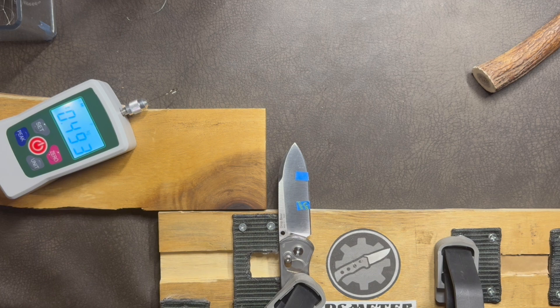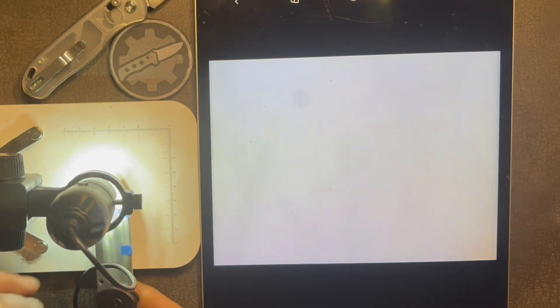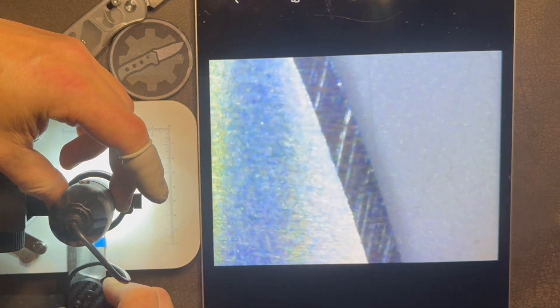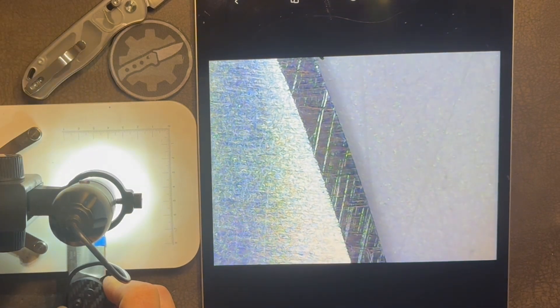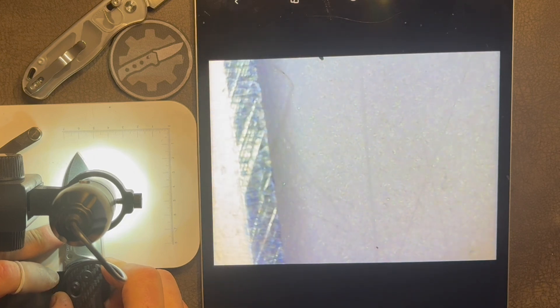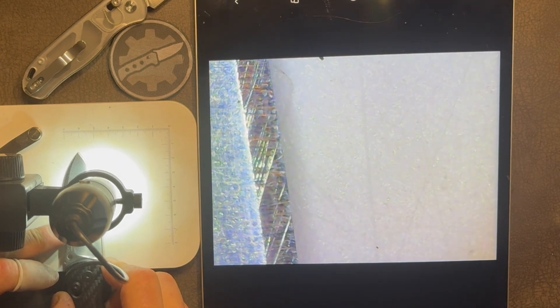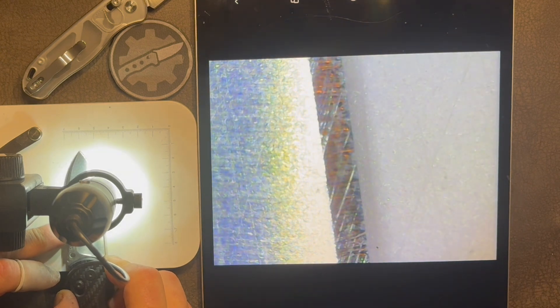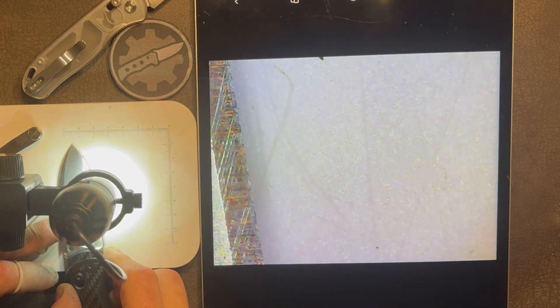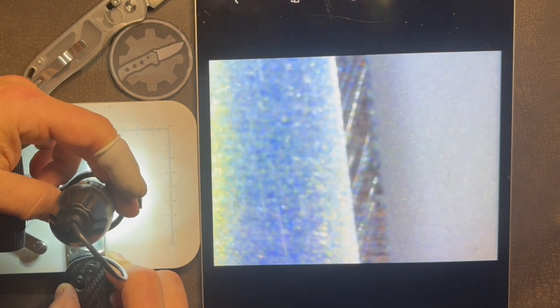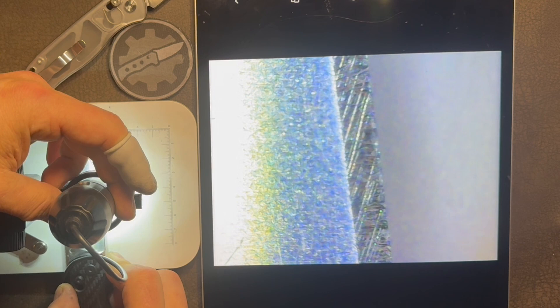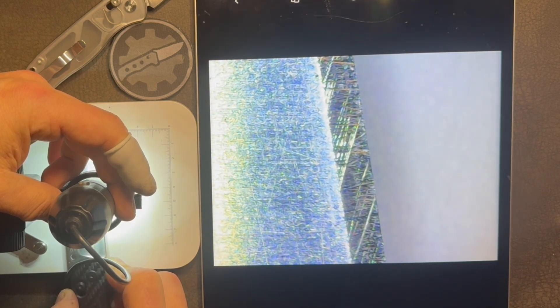As a reminder, I was using the sharpening plates that were labeled to the same grit size, first starting with 220 and 240 on TSProf, then switching to 400, and then sort of breaking or weakening the burr with 1000 labeled media. And the striations you see that are very diagonal, they come from that burr weakening procedure, which tells me that their 1000 media has pretty sizable diamonds included. Okay, let's talk the edge itself. I don't see anything bad happening. There's definitely some material removed from where striations terminate at the apex, but nothing that you wouldn't expect from any knife and any steel after abuse with the buckhorn. Those antlers are nasty to the steel.